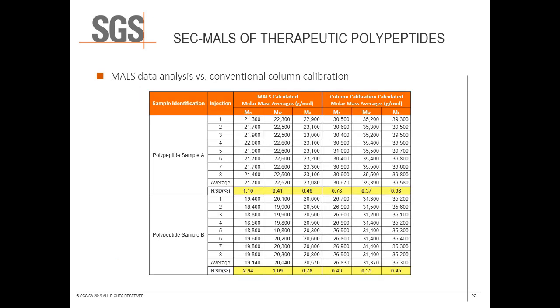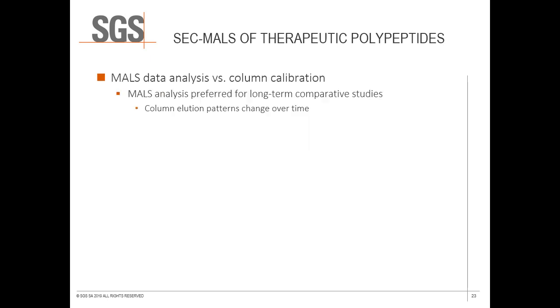Column calibration and light scattering data collected for these polypeptide samples also provide an opportunity to discuss the precision of the two methods. As you can see from the calculated molar mass values of 8 replicate injections of the 2 presented samples, results precision tends to be better with column calibration, which is useful in strictly comparative studies. However, even for comparative studies, MALS may be preferable if the study is to be conducted over a lengthy period of time, as the elution pattern of a column may change as the column ages, and if different sets of columns are used over the course of the study, there could be differences in elution patterns that cause a shift in the data. MALS analysis directly measures Mw, and therefore minimizes these effects.